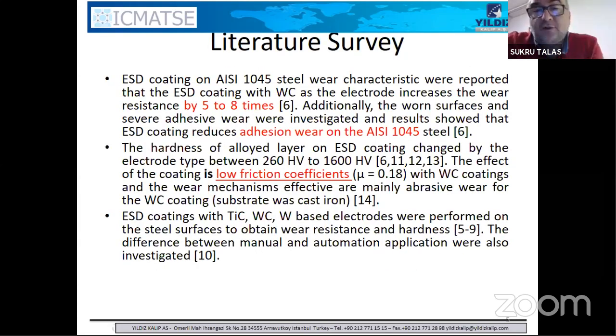So let's talk about coating the surface of this AISI 1045 steel with ESD coating. The ESD coating on these steels is done extensively. As far as the literature goes, it can increase the surface hardness at least 5, maximum 8 times. So you can have 1,000 Vickers, or a little bit over 1,000 Vickers if you have enough thickness of the layer.